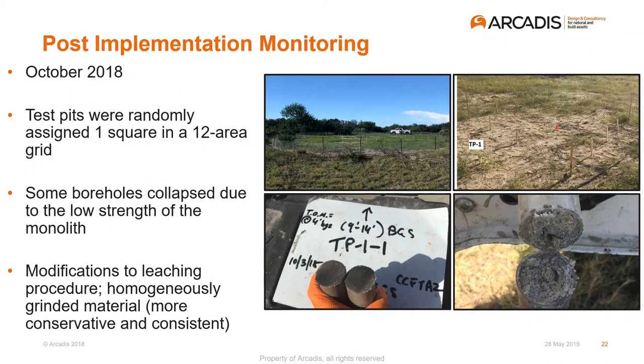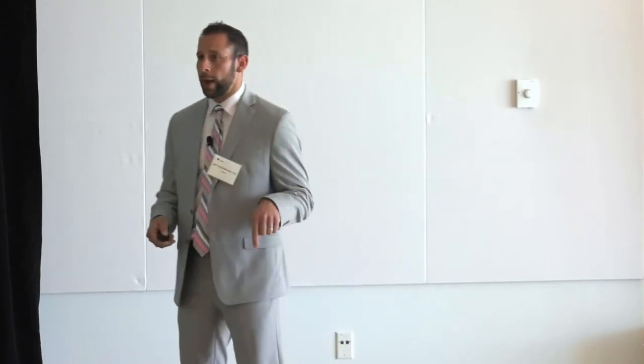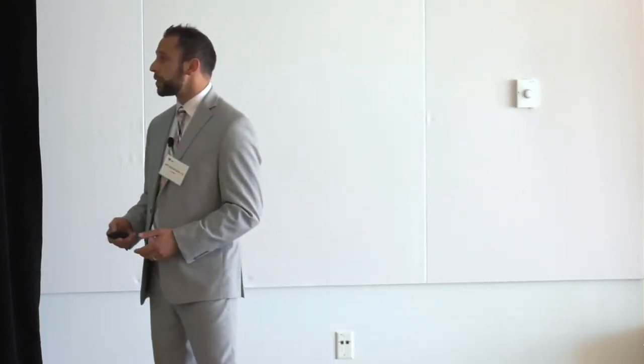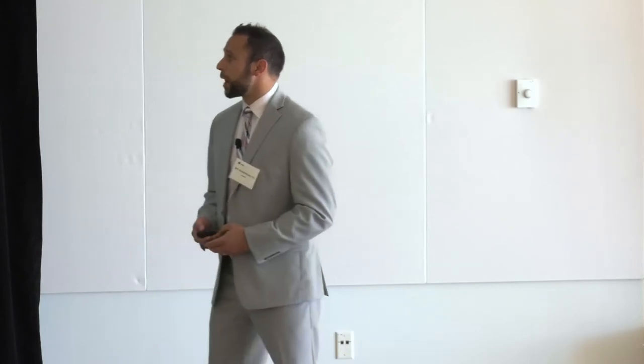We assigned the test pits a random 12 area grid and divided them into three depths. So three vertical depths, shallow, medium, and deep, and 12 grids on top so that we have enough to sample uniquely throughout. And if the mixing was homogeneous, as we hope that it was, the sample should be very consistent throughout, and we're gonna get a great statistical scatter plot when all this is done. And that's basically what we're trying to do.